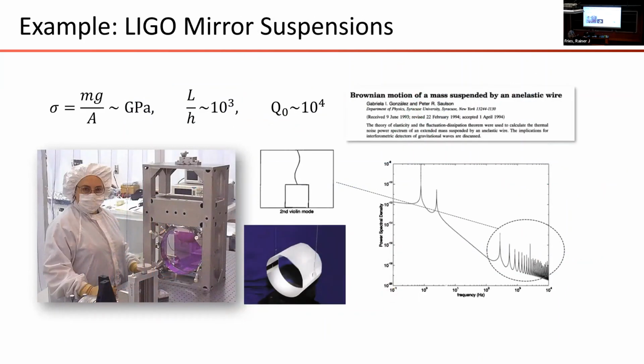Are there any situations in which this dissipation dilution naturally arises? Yes, there are. I alluded to one earlier. The suspension springs for test masses in gravitational wave interferometers are basically optical fibers that are maybe half a meter to a meter long. They're 100 microns wide, and they're loaded on purpose with a 10 kilogram test mass in tension near the yield strength.